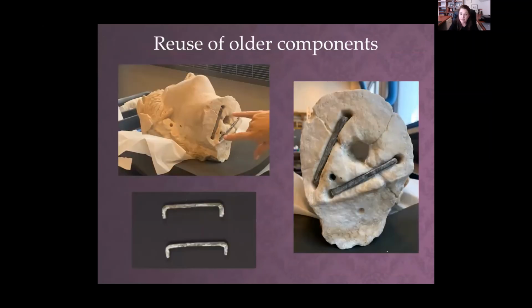Now, some of the pins and metal components we did use again. These are older copper alloy staples that came out of the bottom of the head. Linda Roundhill removed them in 1988. And because they were such a perfect fit for the cavities that were carved in the bottom of the head, we ended up reusing these. So the copper alloy is going to be stable. We did coat them in a barrier material so that they are more stable than they would be. But they fit so perfectly that it was just the only solution to reuse these to secure the pieces of marble in the neck.